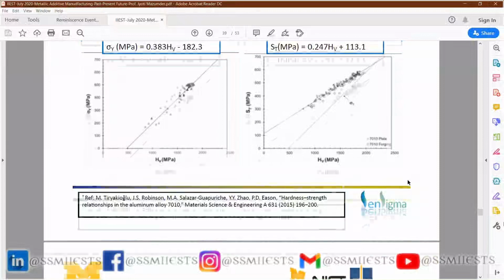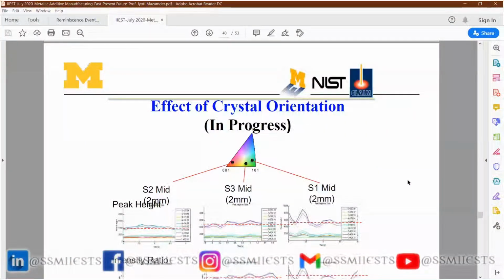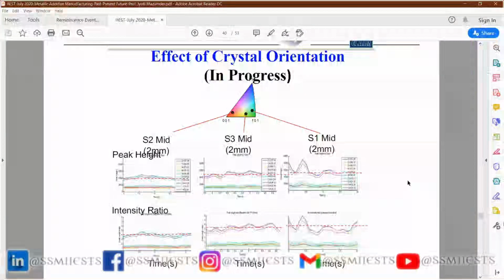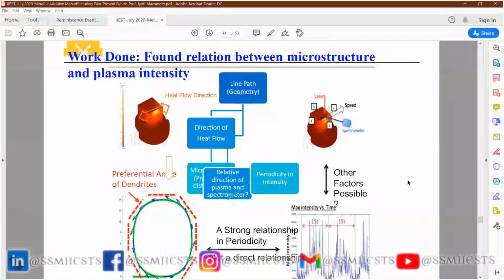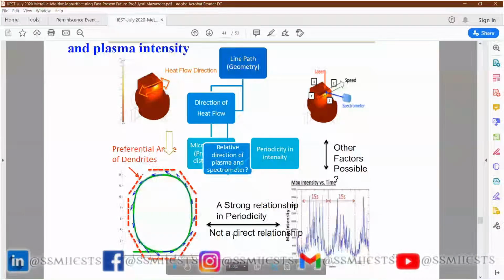We also found that by collecting the light and looking at the ratio, we can give you the crystal orientation too. So what you are seeing here is I'm trying to make you metallurgists unemployed, because most of those things you can find out from the process itself, so you don't have to run to the microscope all the time. And what we found is a quick way to show that when there is a spectrum of strong periodicity, when you are depositing in a circular fashion, we can find the relations of which direction the crystal will grow.